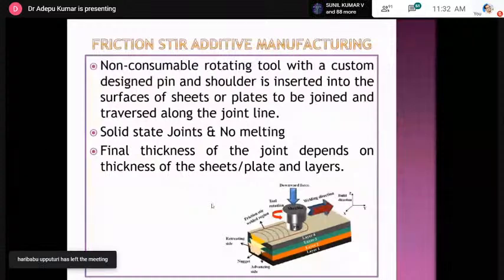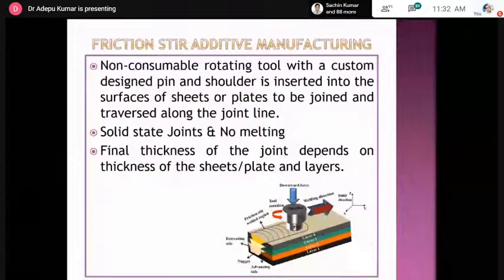It basically originated from the friction stir welding process. In friction stir welding, there is a non-consumable tool with a shoulder and pin diameter. The tool is rotated with a certain RPM, and the shoulder has certain features and the pin also has certain features. The pin is inserted between the materials or in between the layers to be processed. Then the shoulder is always in contact with the topmost layer, and the rotating shoulder generates heat. That heat softens the material, and the material moves from the advancing to the retreating side. Then you can finish the entire process. The same principle you can apply to additive manufacturing, so that you can generate the components.